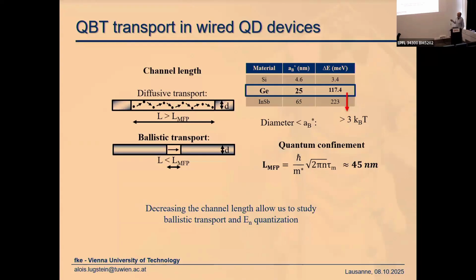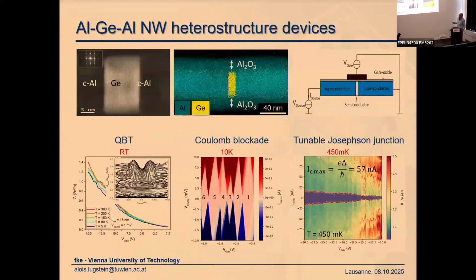In addition, these nanowires were really thin. Happily, the Bohr radius of germanium is quite large, and the spacing of the subbands is rather large, much larger than these 25 milli-electron volts, which corresponds to room temperature. And therefore, we were able to observe quantum ballistic transport at room temperature for these germanium nanowires, the one that is shown here. You see nicely here this plateau at G0 of 1, and even the waterfall plot shows this quantum ballistic transport behavior. If you cool down this structure down to 10 Kelvin, this germanium dot remains